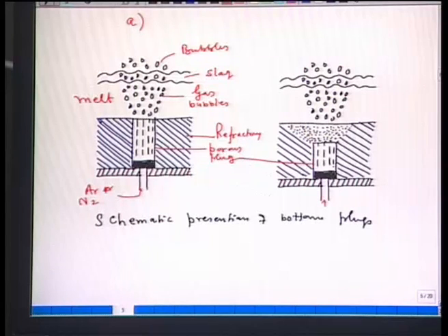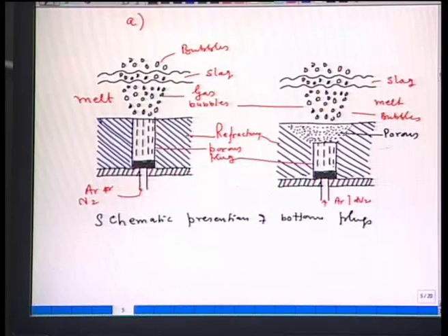this is again the porous plug. From here argon or nitrogen, this is the refractory lining, these are the gas bubbles, this is the melt, this is the slag, and these are the bubbles. Now, what has been done in this design? The refractory plug is shorter and the distance between the bottom of the melt and the plug is rammed by a porous refractory mass. So, in fact, this thing which is being shown over here, this is a porous refractory mass.